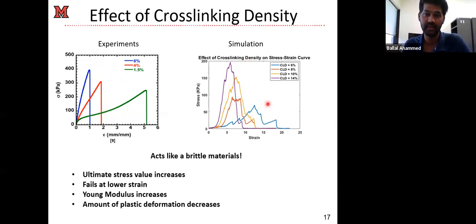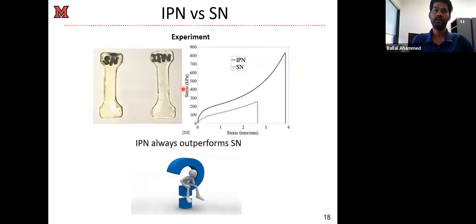When we did the same simulation, we found a similar trait. When you increase the cross-linking density, our peak stress value increases, and the failure becomes more brittle-like. That means our model is working, because we're getting a similar trend. It is able to capture the physics that's happening inside the material. So that's a good sign. Let's move forward.